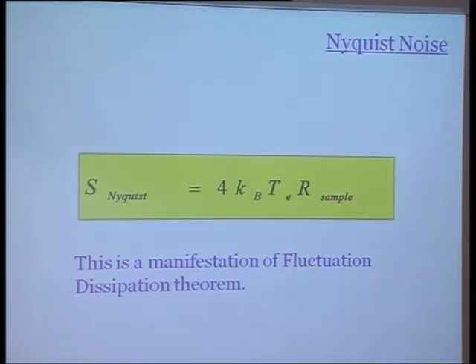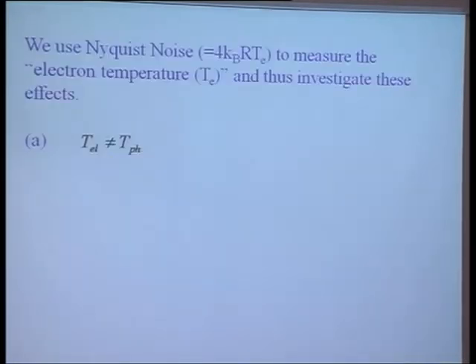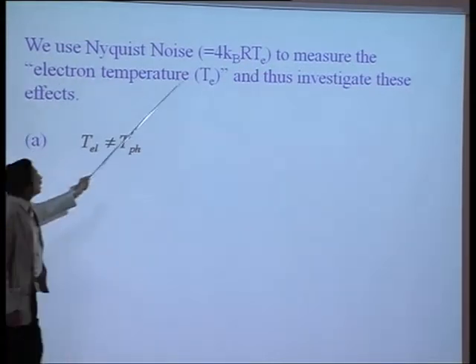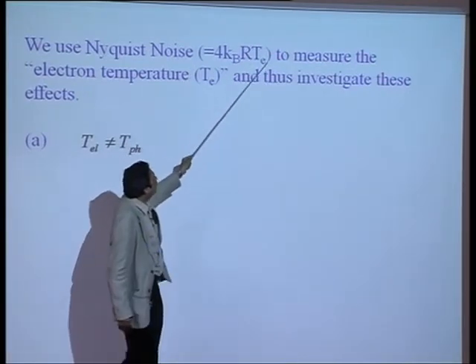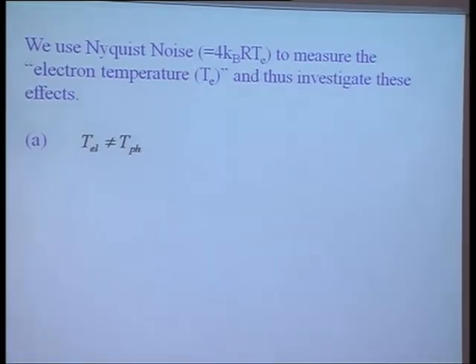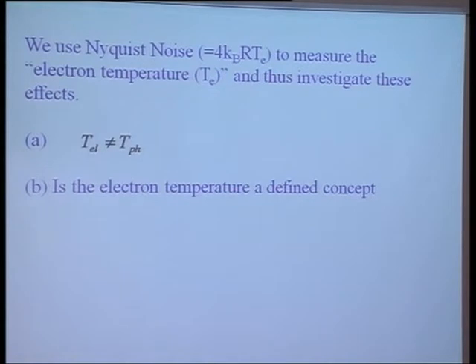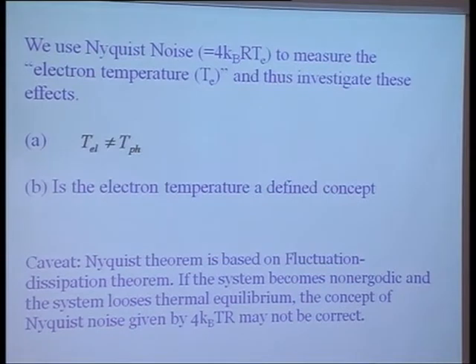So my question is, are we seeing something like that? And this is a region of unknown. So two things we can investigate using the Nyquist noise. I can use it as a thermometer and measure the electronic temperature and compare that to the phonon temperature and find out whether they are differing. Or I can find out whether the electron temperature is a defined concept or not. So the main caveat over here is that this Nyquist theorem is based on the FDT, and if the system becomes non-ergodic, the system loses thermal equilibrium and is not going to give you 4kBTR.